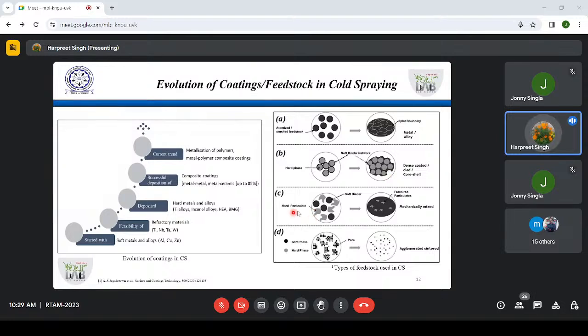One way of doing these kind of composite coatings is that you have a soft binder and hard particles. You just blend them and then deposit them, and you will get this kind of morphology. But here you have more control over this phase. Then there is another approach where we have a soft phase and a hard phase. These are sintered, and then we deposit them, and we get the final microstructure having both these phases.